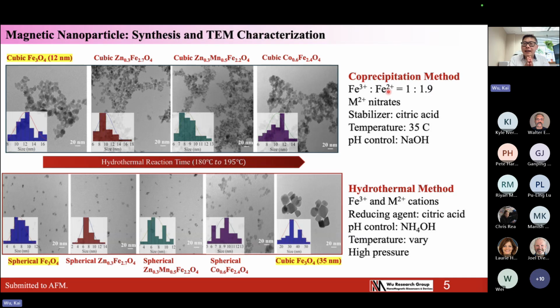So the fundamental part is that we are doing some doping on this iron oxide to change the dynamics of these particles for hyperthermia treatment, magnetic particle imaging, or biosensing applications. So we do a small change and the outcome on the application will vary a lot. In the co-precipitation, as you can see, we can generate a large amount of particles, but the particle shape and size is difficult to control.